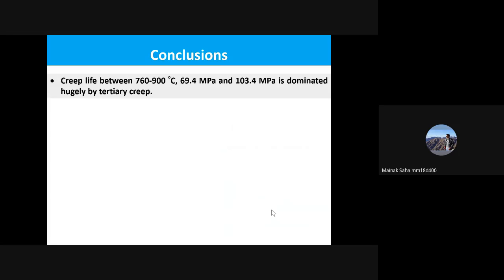So with this, the present work concludes a few things. That is, the creep life between 760 and 900 degrees and between stress levels of 69.4 and 103.4 MPa is dominated hugely by tertiary creep.